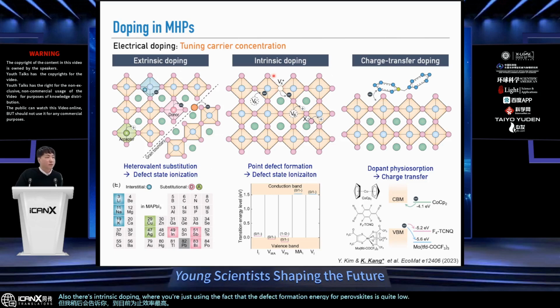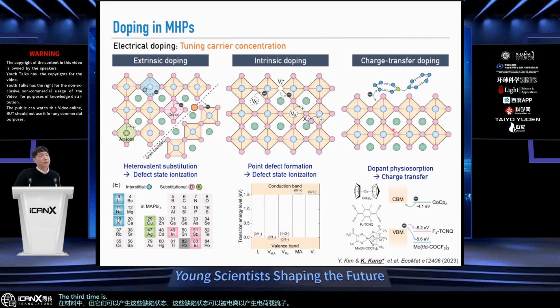Contrary to what many people believe, that these perovskites are defect tolerant, they are by properties, but there are defects because the formation energy is very low. For example, the halide vacancies, there are so many of them, which can cause ion migration in the material, but they can create these defect states that can be ionized for creating charge carriers. The third type is more the charge transfer doping type, where you are using dopant molecules, for example, where there can be charge transfer between the host semiconductor and the dopants, such that via this energetic driving force, you are trying to drive some electrons from host to the dopant, which will be p-type doping. The reverse will be n-type doping.